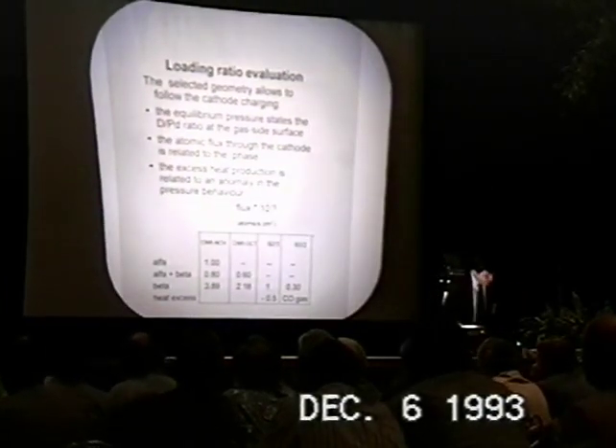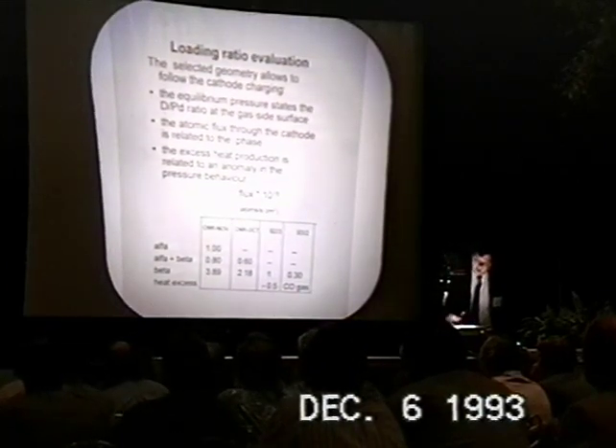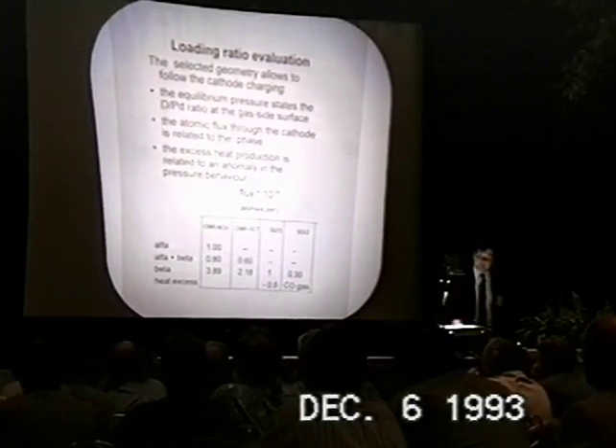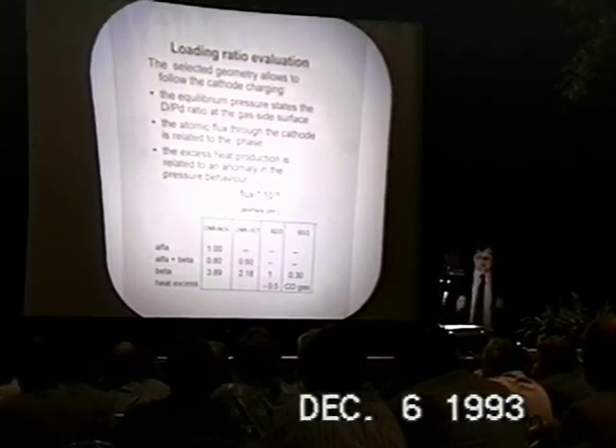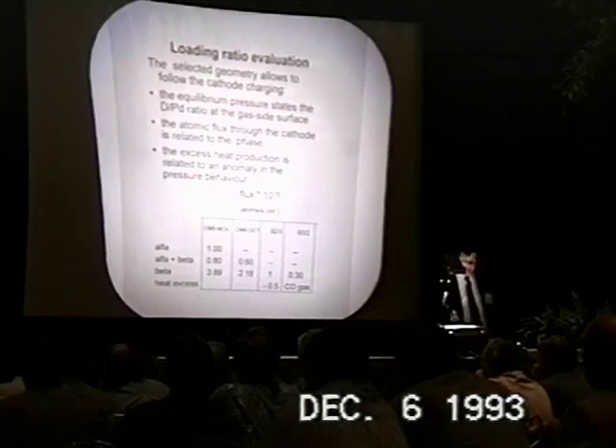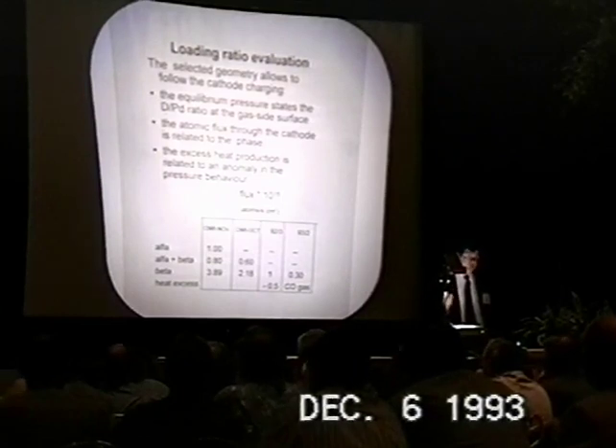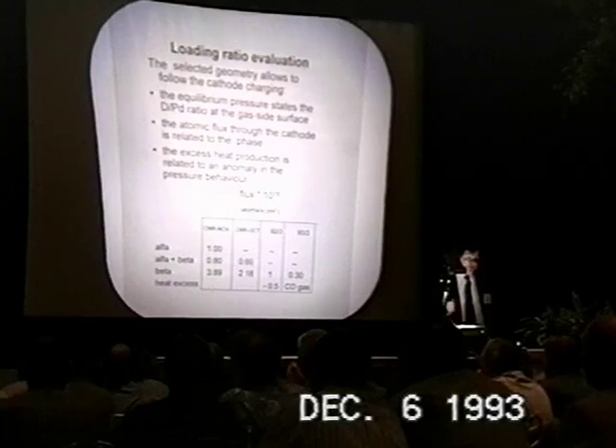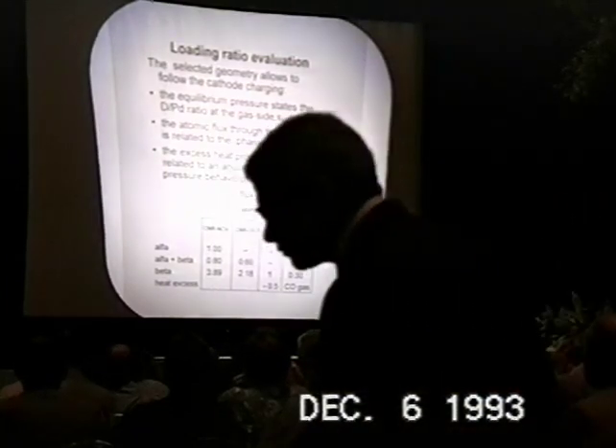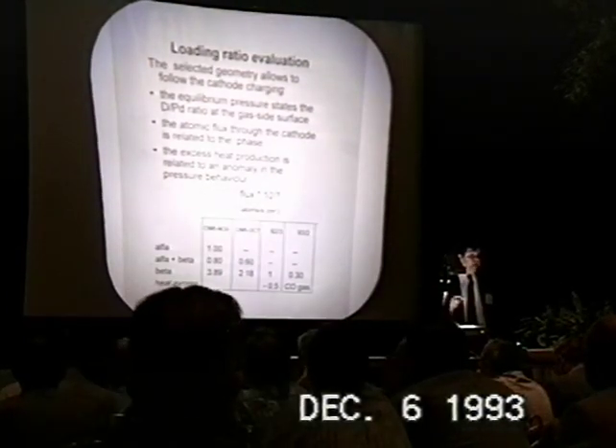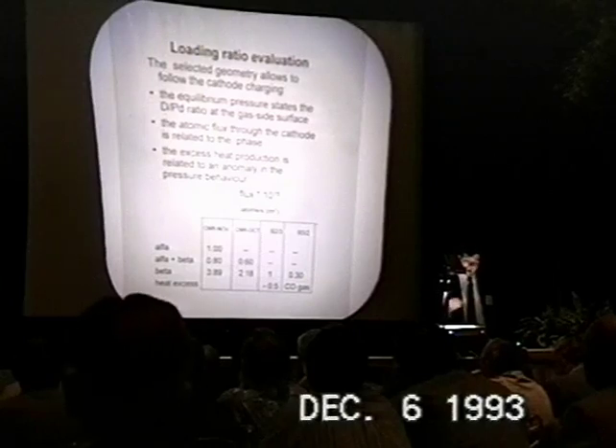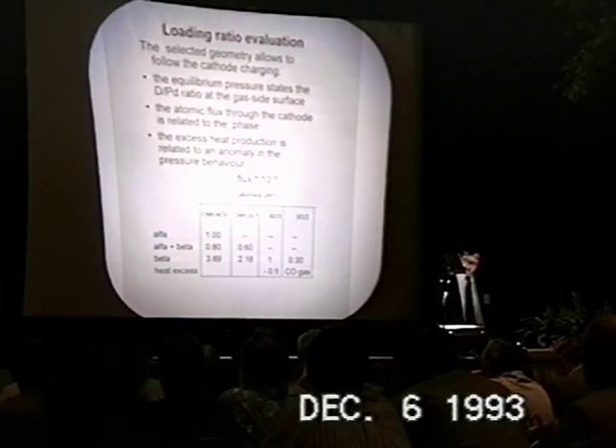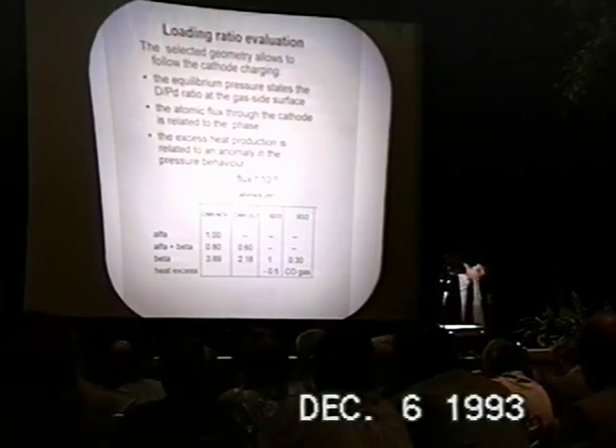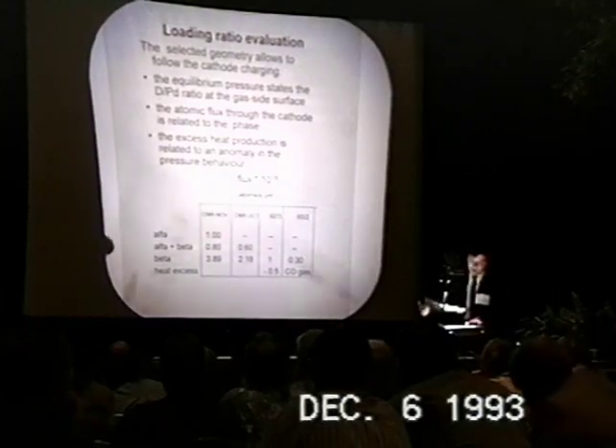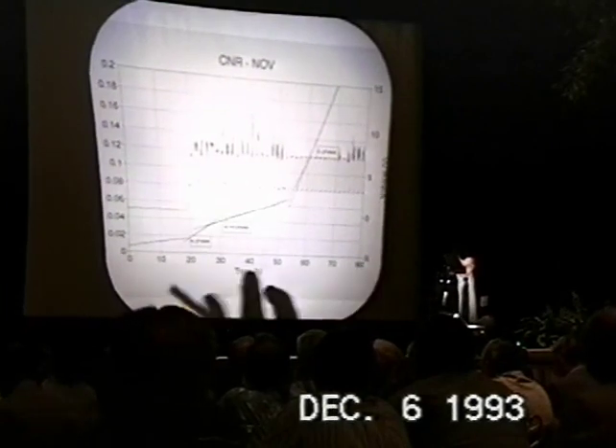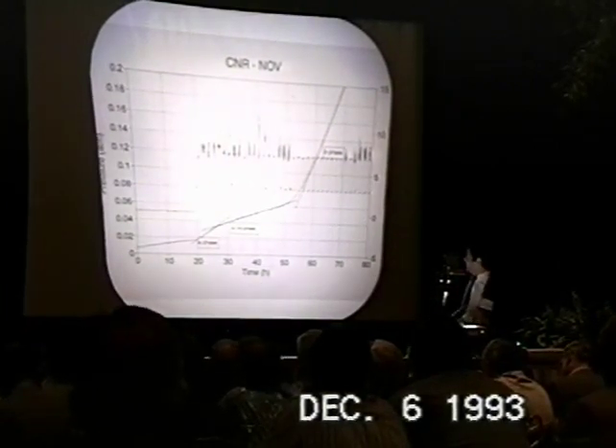Here are some preliminary results on the loading ratio evaluation. As I told before, this particular geometry allows to follow the cathode charging. So the equilibrium pressure behind the cathode gas surface states the D/Pd ratio. We can measure the atomic flux, and so we can find a relation with the phases of the charging. And then we have seen last year an anomaly in the pressure behavior. I would like to show you this plot.